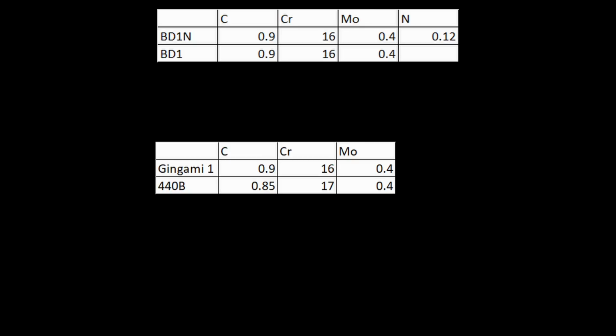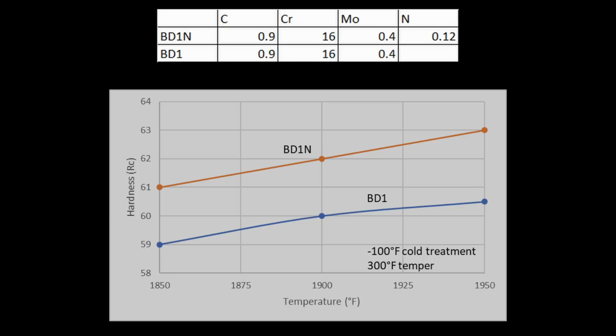Yeah, so BD1 is essentially a 440B type steel. It's on the low end for chromium. The 440 spec is 16 to 18 chromium, and BD1 has a target of 16. But otherwise, it's essentially just a 440 type stainless. I've got a chart from Carpenter's own data where they show BD1N and BD1 versus austenitizing temperature. I just plotted it out so it's easier to see. This is with a cold treatment after quenching and then a 300-degree temper.